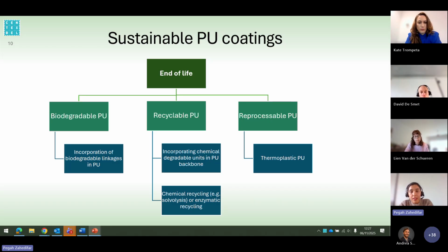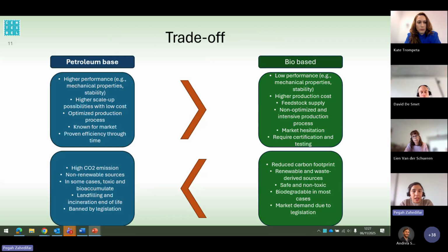So for example, if we have the thermoplastic polyurethane instead of the thermoset one, then we can reprocess it and reuse it. But when we are going for the bio-based alternatives for the production of the polyurethane, we are achieving some good aspects, but we are also losing some of the properties. For example, with the petroleum-based one, the performance of the final polyurethane is much higher with regard to the mechanical properties or stability, and the process for scaling up is already optimized in the industry, so we can have better scale-up productions, and it is more known to the market, so people are more willing to buy it at the moment, and the efficiency is also proven.